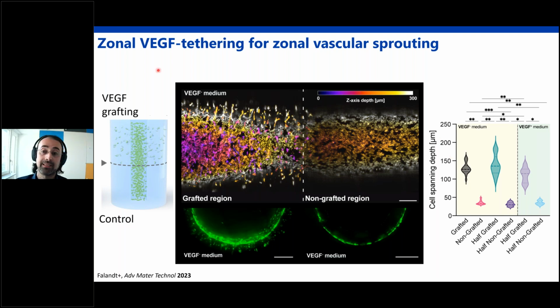Indeed, we can see that this happens both in the presence or absence of VEGF in the media, indicating that the grafted factor is still potent, even in the presence of an abundant, homogeneous distribution of this growth factor all over the construct if you apply it also in the media. So this is a powerful, interesting technology.